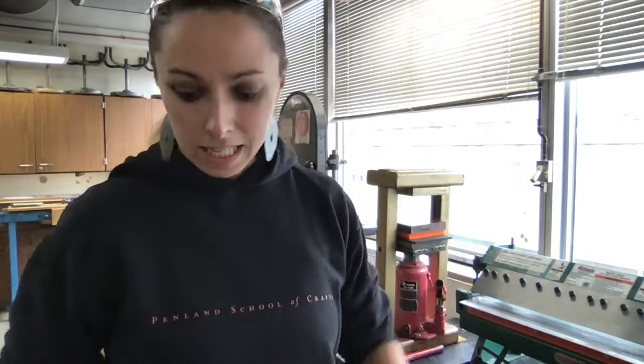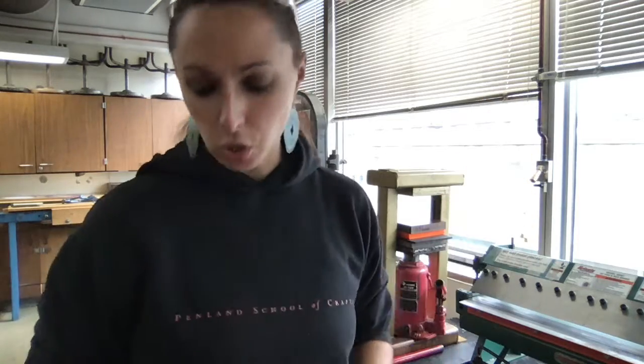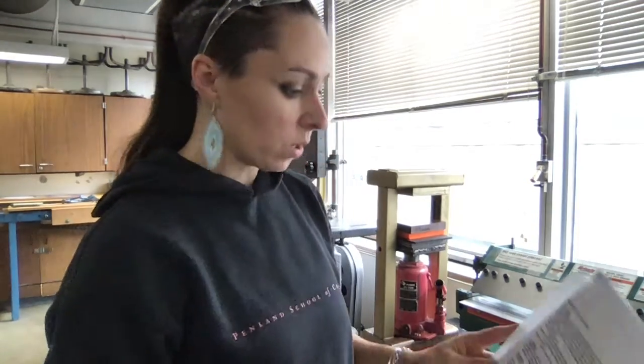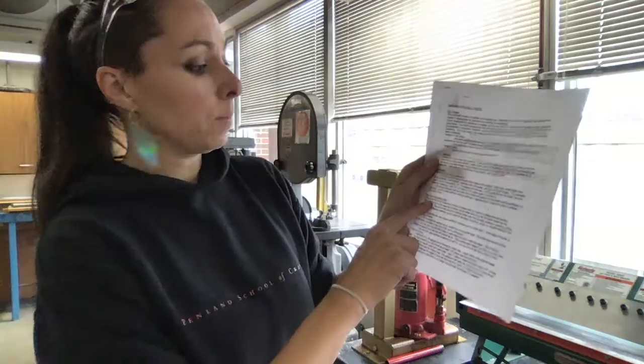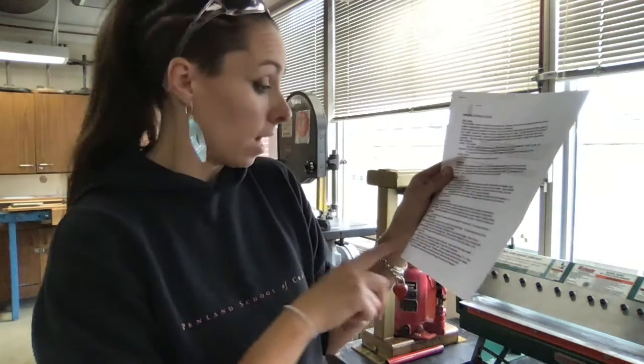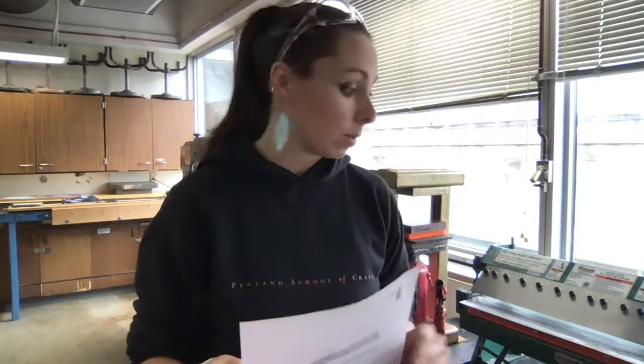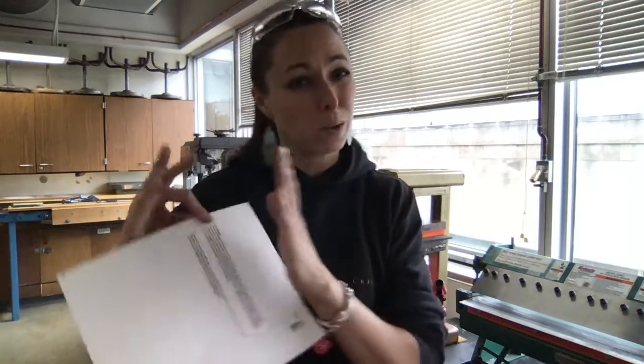Okay, now I have my annealed metal, I have my die. I have 2 dies that I'm going to be showing you guys. And after you cut your die or while you're cutting it, be sure to refer to the Use Hydraulic Press handout. It has a bunch of tips for creating your non-conforming die and rules of thumb for what you're looking for when you're cutting your die. It includes directions and reminders about how much material you need on the outside, 1/2 inch to 1 inch. I like to do anywhere between 3/4 and 1, just to make sure that this die is going to last a really long time.